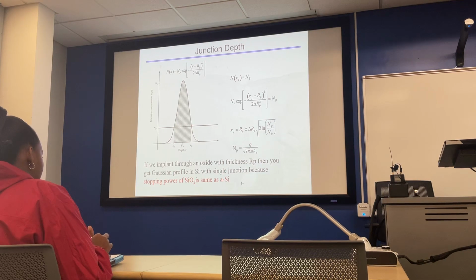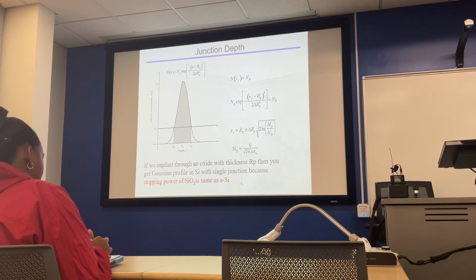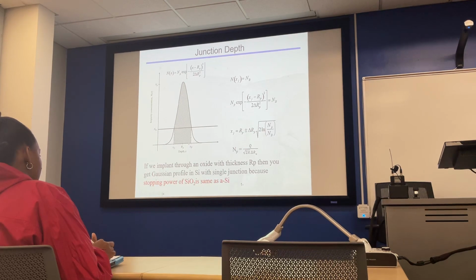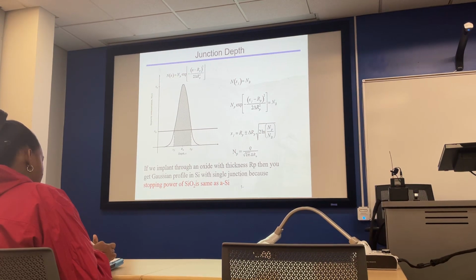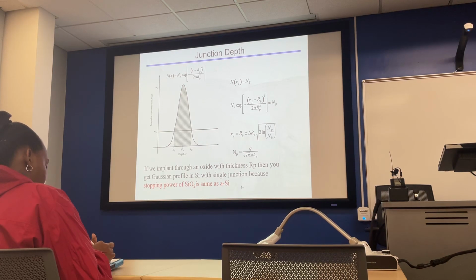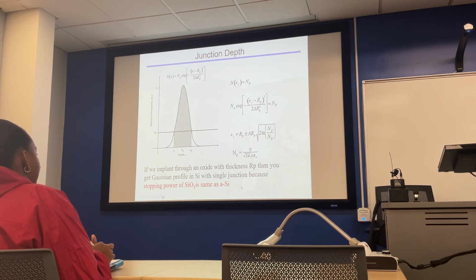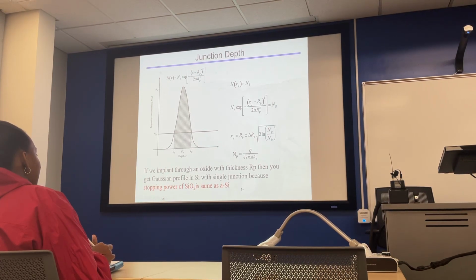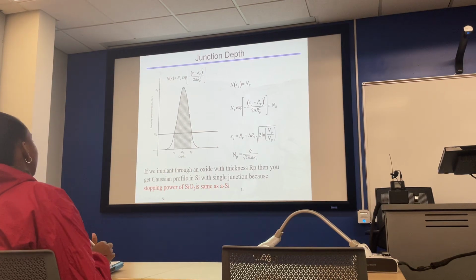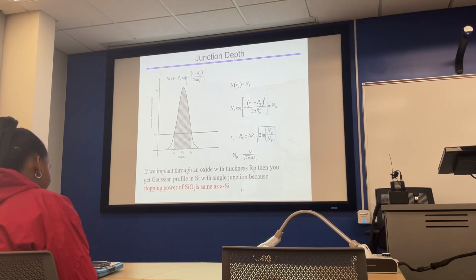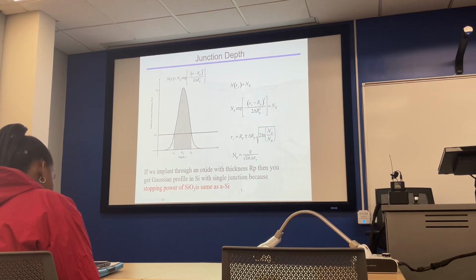Okay, so this is a real problem. This is a real life thing I'm talking about. As I told you, the real life problem is how do I get the junction depth I need? The nice thing here is I have a pretty good control of my junction depth, because I can play games with the oxide thickness, right? So I have a very good control over this. But the problem is then the requirement for the surface concentration, when you make the source and drain, right? You need a certain surface concentration. If that is not met, then I have to get a different profile.